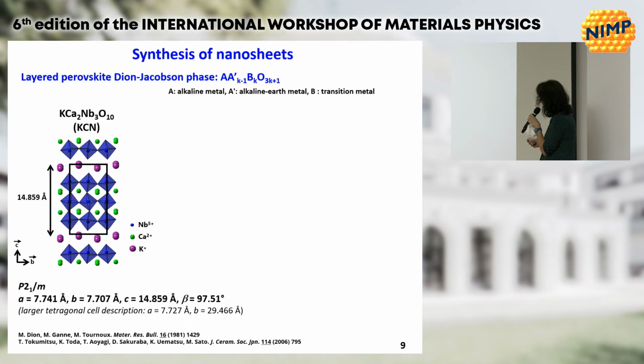So we start with the synthesis of the nanosheets. To obtain these nanosheets, first we start with a parent compound, which is a layered perovskite, Dion-Jacobson phase, with this chemical formula we have here. In these compounds, we have potassium, calcium, niobium, and the structure you can see here is made of sheets constituted by three layers of octahedra sharing their corners, as in a perovskite. The thickness of the sheet is about 1.5 nanometers. And in between each sheet, we have a layer of potassium.